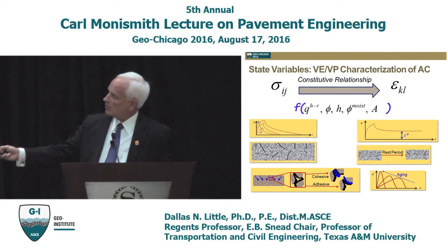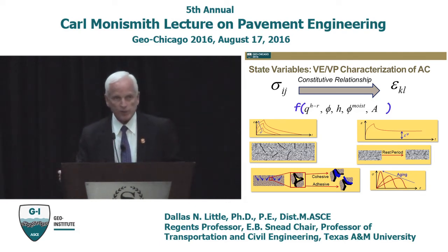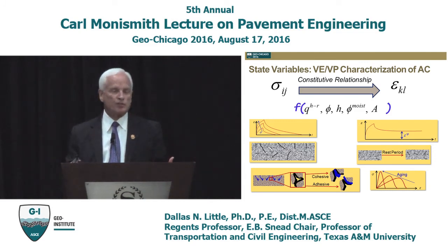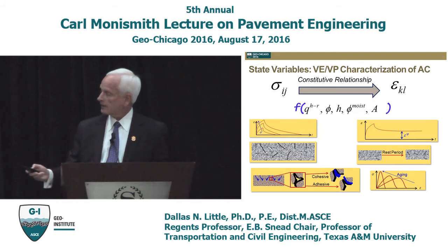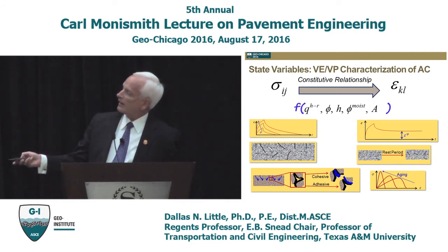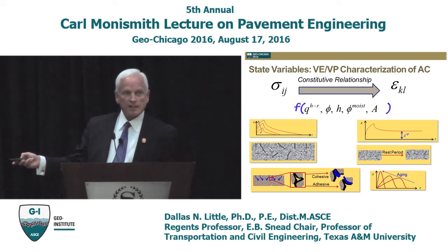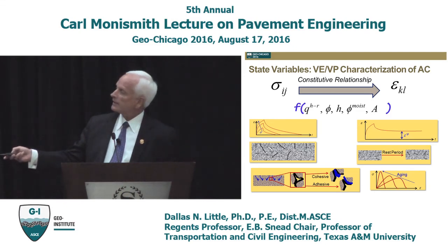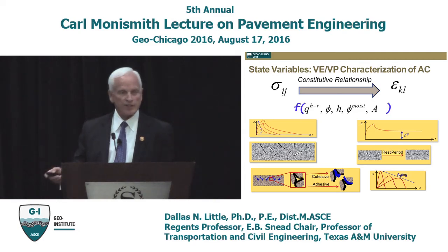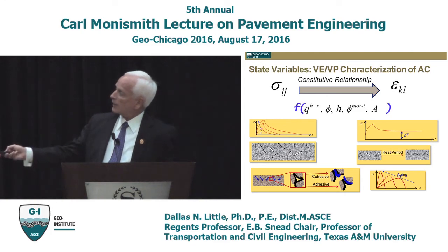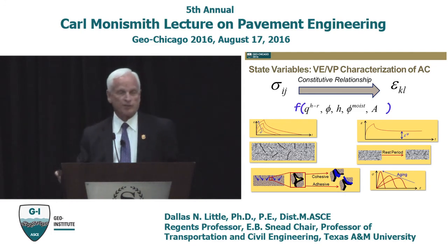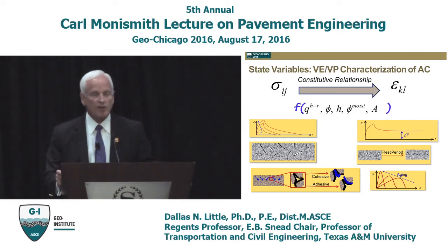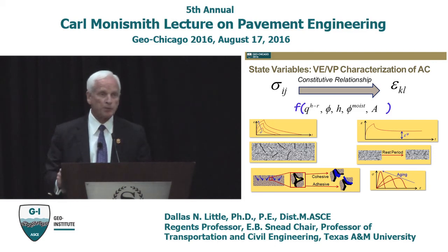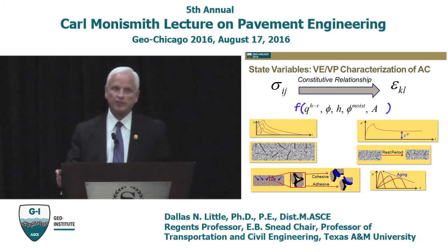And then there is the phi with the superscript moisture, which stands for moisture damage as moisture diffuses into the matrix of the asphalt and compromises the cohesive strength as well as the adhesive bond strength. And then finally, the last state variable is aging. You can see down here when I talked about the moisture moving into the system, the asphalt composite, it compromises the strength of the mastic, and when it gets to that interface, it compromises the adhesive bond as well. When aging occurs, aging stiffens the mixture. It stiffens the mixture by oxidative aging, by hardening, and makes it often less susceptible to plastic deformation, but more susceptible to the process of fatigue damage.